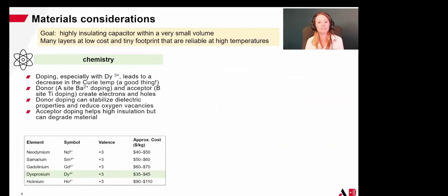Now, one way to achieve that is by doping, and that involves modifying the chemistry of our barium titanate matrix to change the properties. And one of the ways to do that is doping with rare earths, particularly dysprosium. This is a really interesting element because it has a 3+ valence state, so it can substitute at the A sites for barium 2+ or the B sites for titanium 4+ and act either as a donor or an acceptor. Now, donors are needed because we need to have stabilized electric properties and reduce oxygen vacancies. The acceptors can really contribute to improved insulation properties.